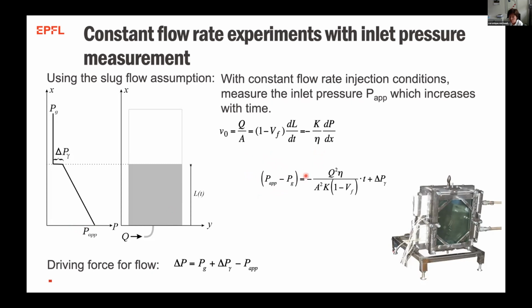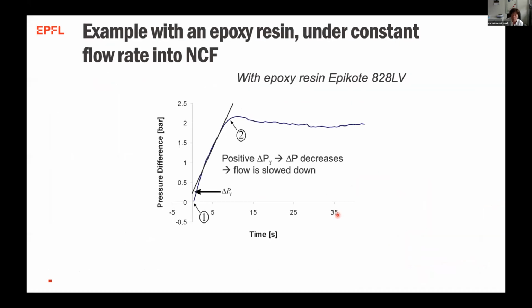And if you measure this pressure, you will see a linear increase with time, which gives you actually the permeability as well, if you know everything else. And there will be a plus delta P gamma, which will tell you what is the value of delta P gamma. So if you do different experiments with different flow rates and so on, you should be able to find what is delta P gamma with the flow rate. And we did these different tests, and you see that it kind of works.